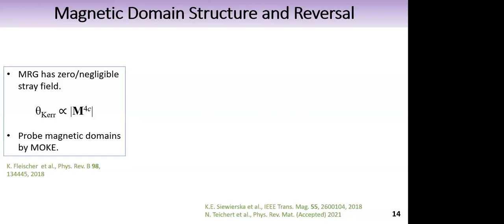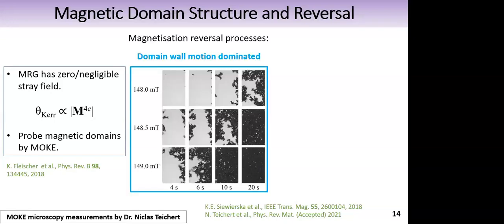But we use the fact that the Kerr rotation is proportional to the manganese 4C sublattice magnetization, because only the electrons on the manganese 4C sublattice contribute to the transport. And therefore, it is possible to probe magnetic domains by using a Kerr microscope. And so I'm going to show you some domain images.